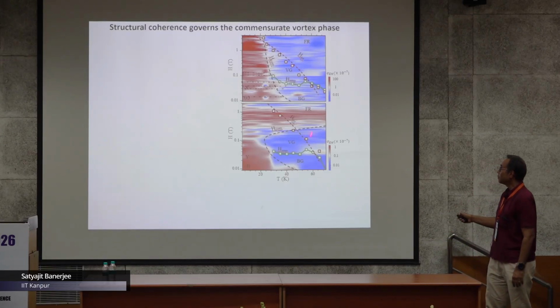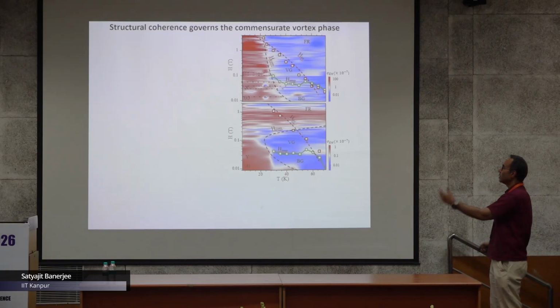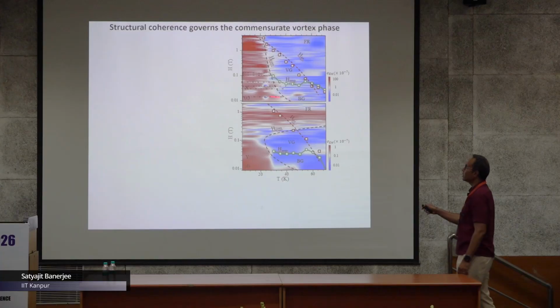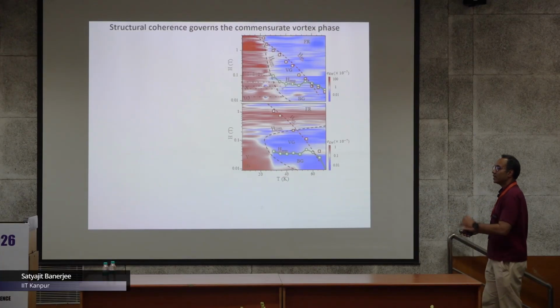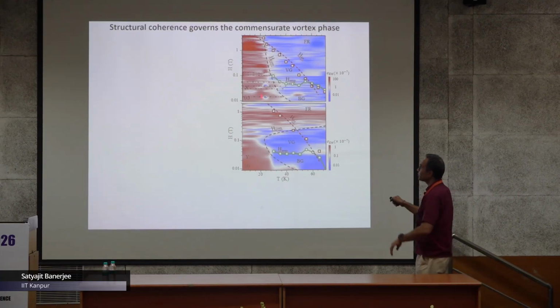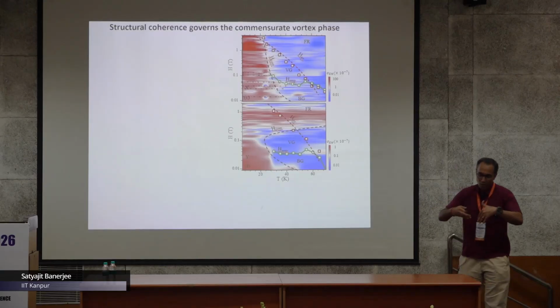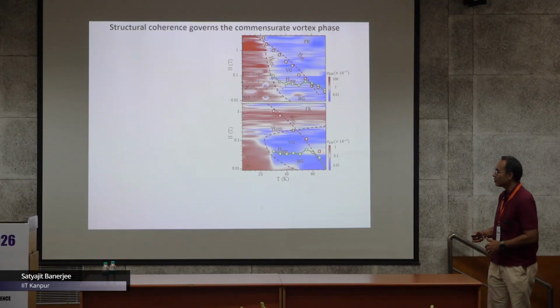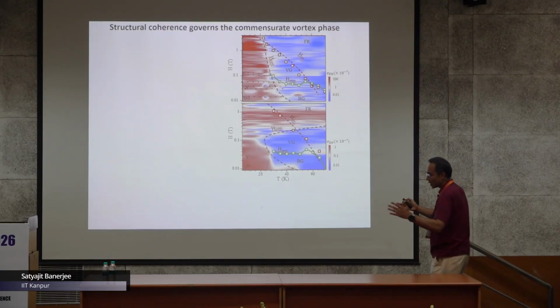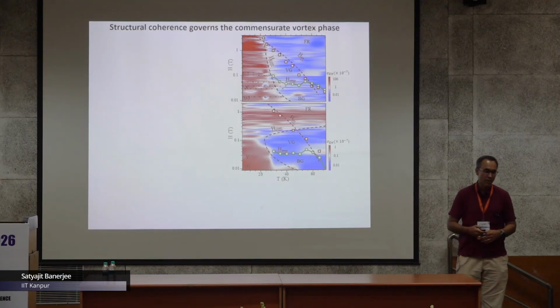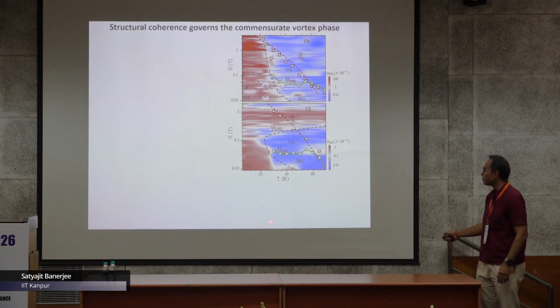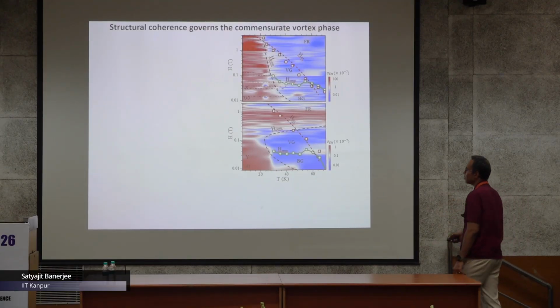As you go to sample Y, where the system has been thermally annealed, all these modulations are gone. It has become more or less a different sort of pinning potential—not periodic, but closer to random pinning inside the sample, and these features are removed.